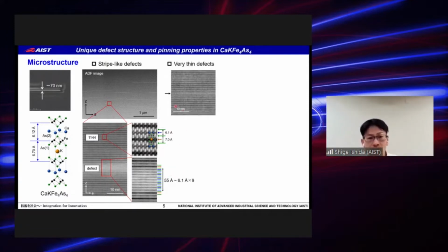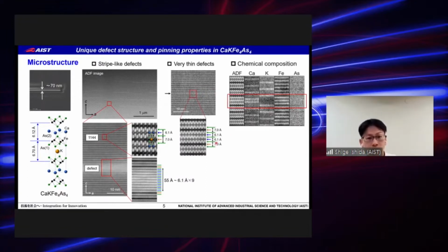Furthermore, by carefully investigating the microstructure, we found much thinner defects, which are identified to be the monolayer calcium 122. Chemical composition analysis also supports that these different defects are calcium 122 intergrowths, where calcium is rich and potassium is poor.